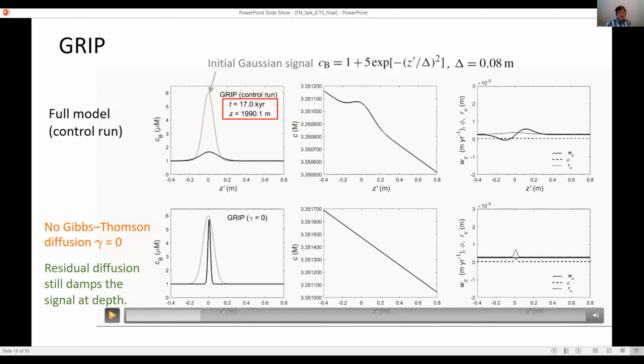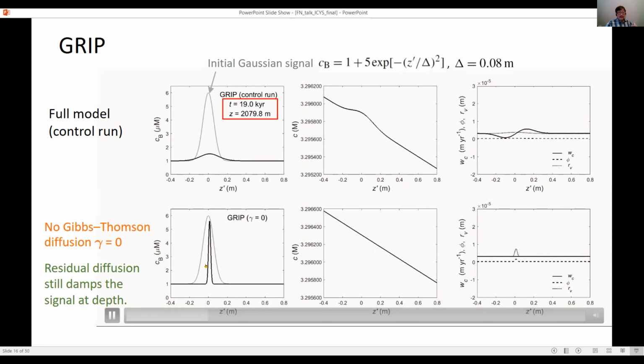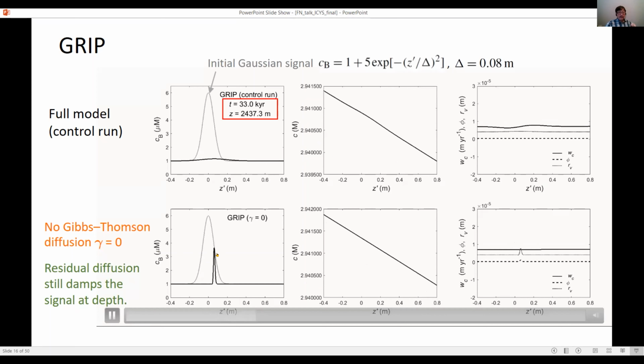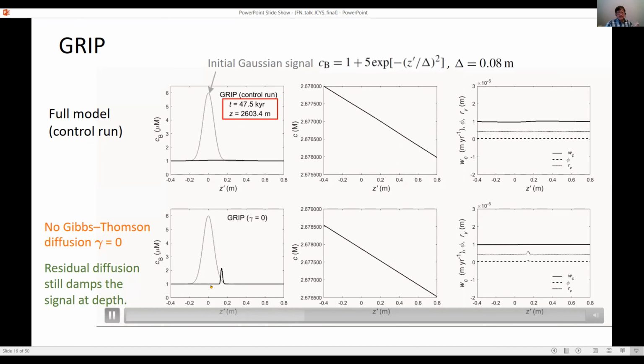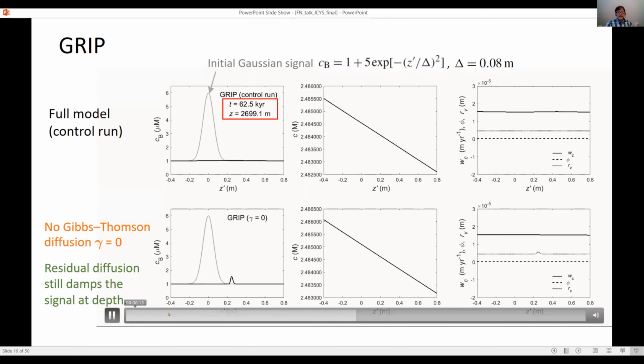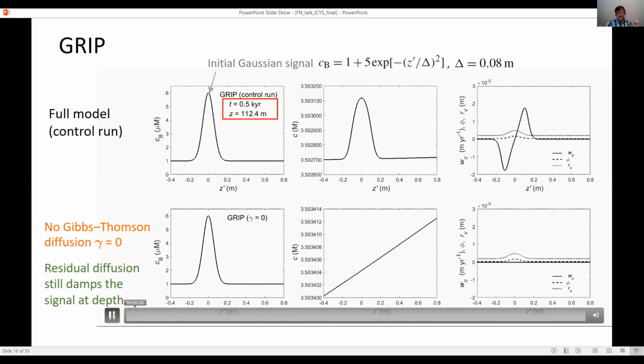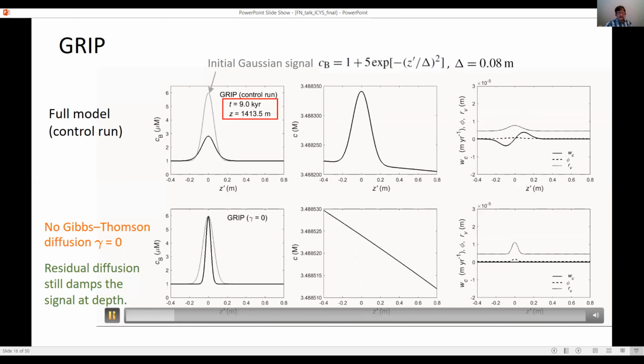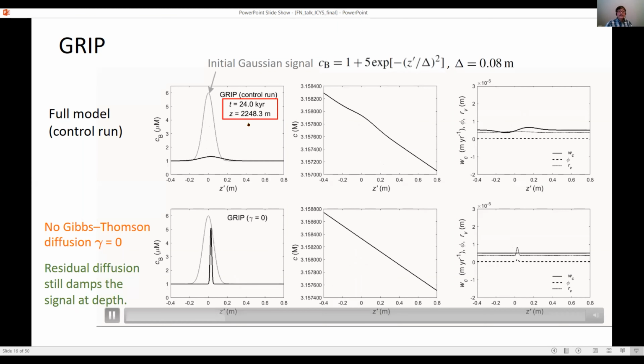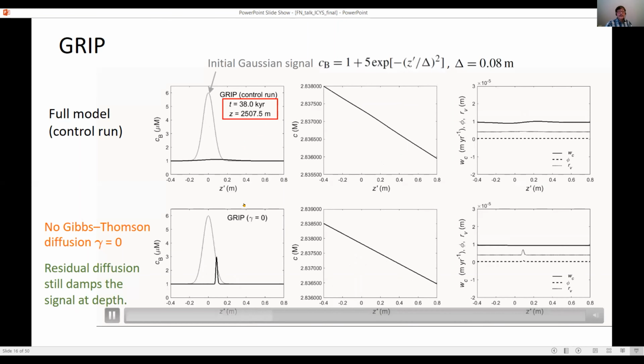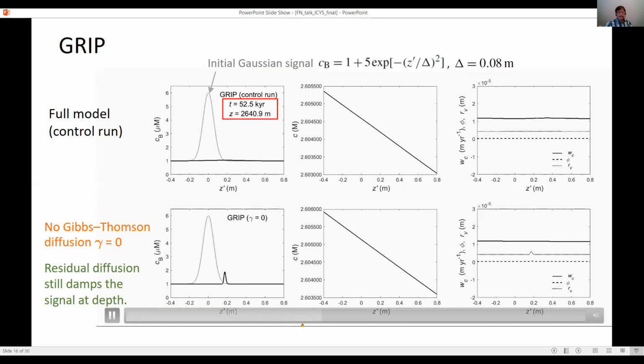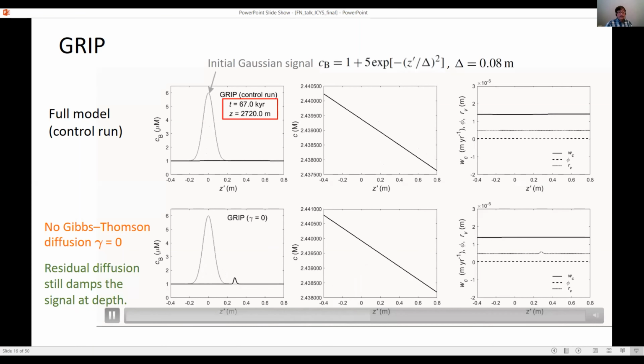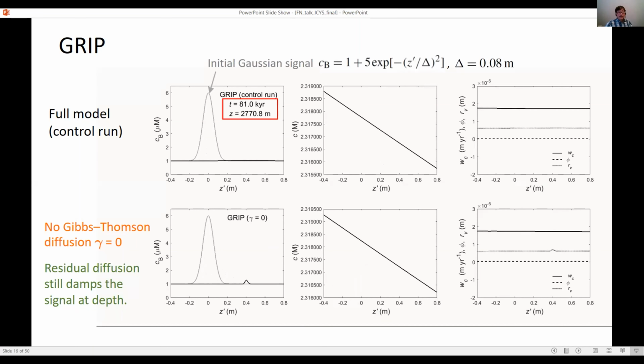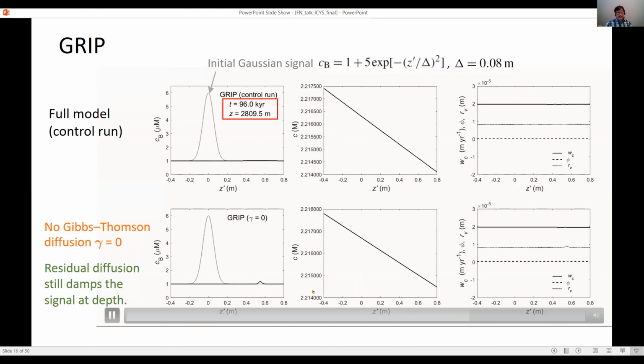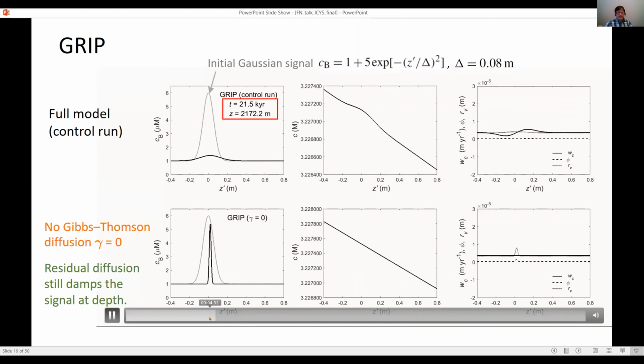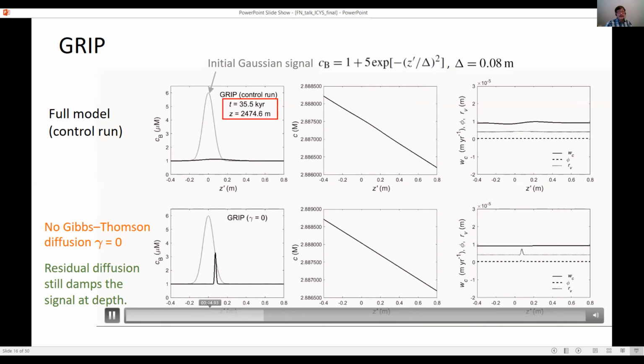When we switch off the Gibbs-Thomson, this is approaching Rempel's theory now. The signal amplitude survives longer. We're now able to see the migration. The signal still decays though, because of residual diffusion, which we didn't switch off. And this is coming from grain boundary motion. So let me play this through. This dial up here applies to both simulations. Migration rates are high towards the bottom of the GRIP core because of the high temperature gradient there. But essentially halfway down the column, we've lost the signal, the integrity is lost.